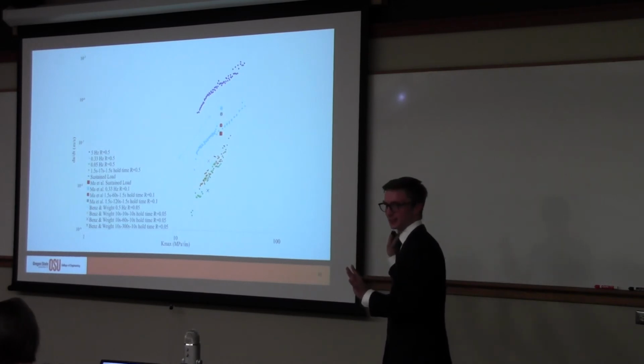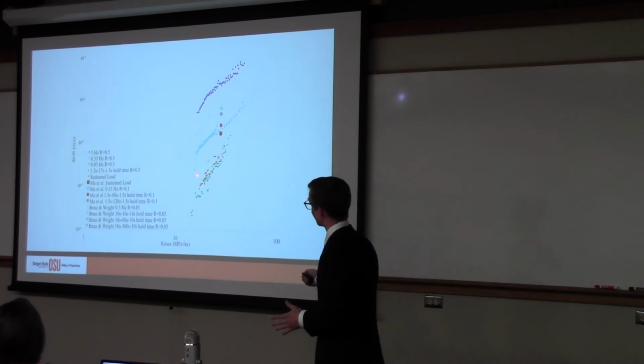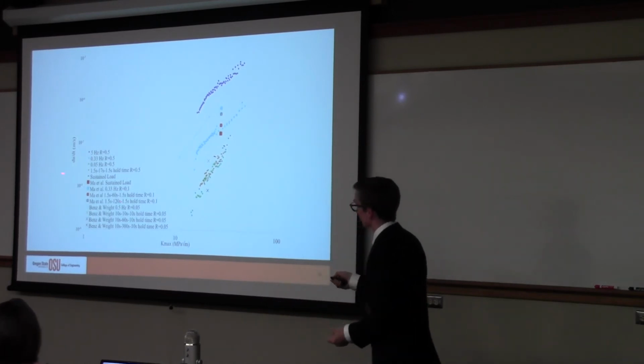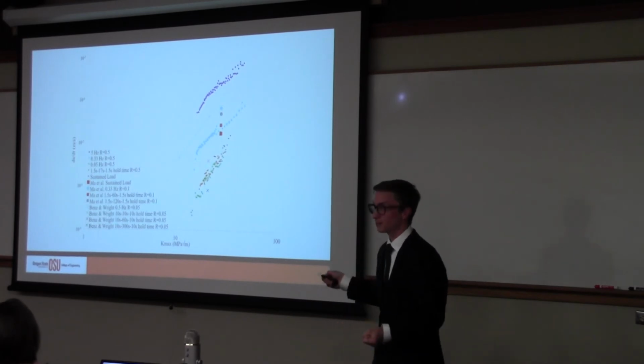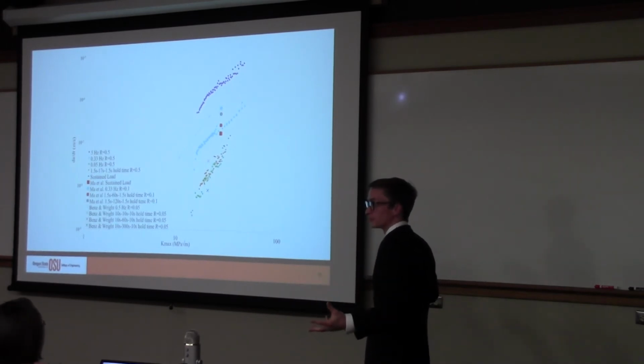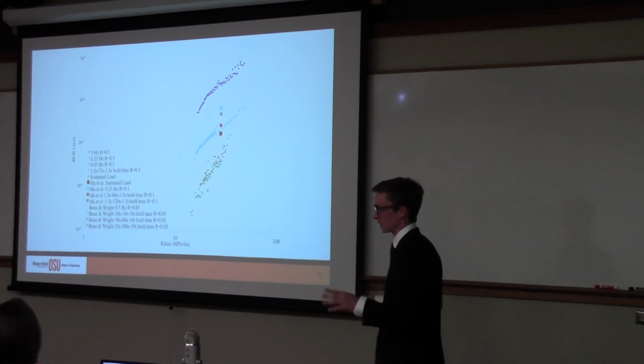I'd stare at this for quite a while before I get that their data is collected right below the transition. Right below the transition to time dependence. So of course you're not going to see faster crack growth rates with time, okay? Because the time-dependent crack growth mechanisms are not active. But they did apply their tests in exactly the same way Ma did to the same sample.